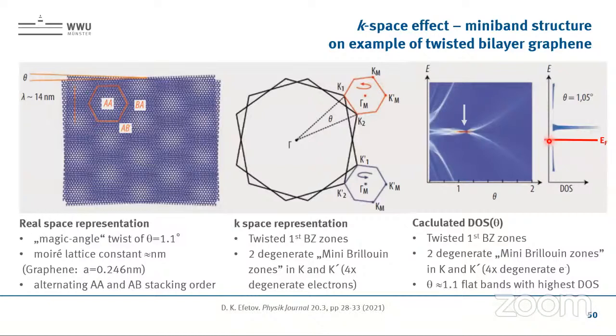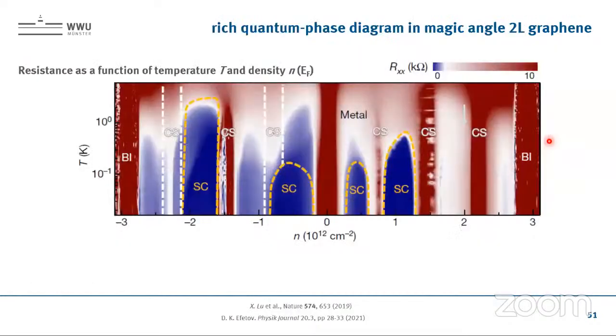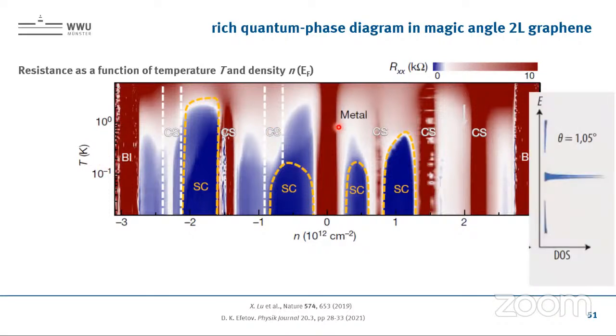And now if you tune the Fermi energy in a field effect structure through the states, you can see about the properties. And this is a very rich physics which is coming into play. So here is plotted the temperature versus the density, so meaning the position of the Fermi energy, and the resistance is color coded. So you see you have some domes where we have superconductivity, we have regions where we have an insulating phase and some regions in between.